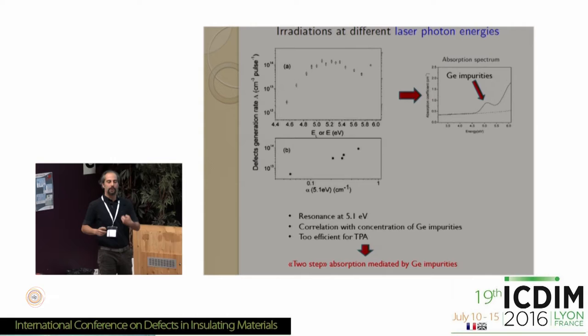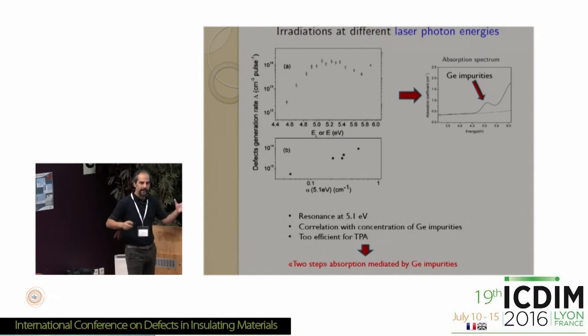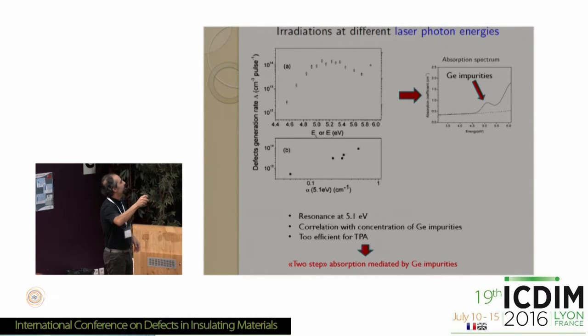Essentially, we measured the generation rate of the defects as a function of laser wavelength or photon energy, which is the same thing. And as you can see in this plot, we actually observed a peak in the generation rate at about 5.1 electron volts. Now, the absorption spectrum of the sample has a peak at around 5.1 electron volts, which is known to be due to germanium impurities. And also we found that the generation rate of the defects is linearly correlated to the concentration of these impurities.